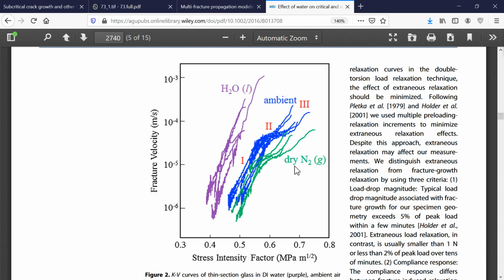And this subcritical fracture propagation is partially driven for that effect by corrosion at the tip, or degradation of the properties at the tip of the fracture. So that if you have different fluids, the response is going to be different. The subcritical index is going to be different, and also the toughness could be different depending on in which medium